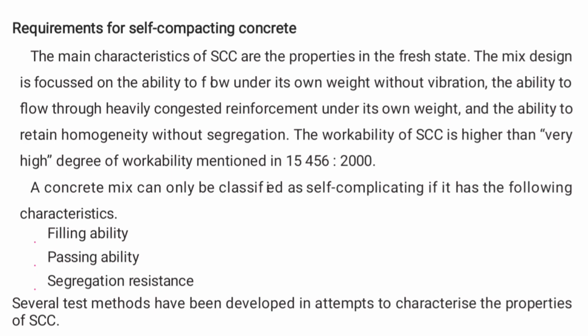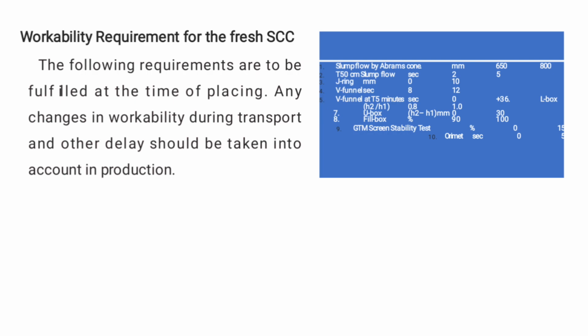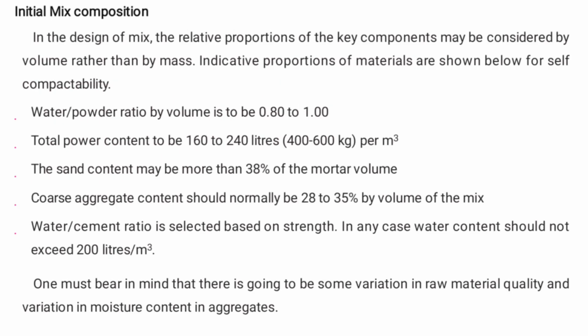A concrete mix can be classified as self-compacting concrete if it has the following characteristics: filling ability, passing ability, and segregation resistance. The workability of the fresh self-compacting concrete is fulfilled at the time of placing. For the initial mix proportion, the water powder ratio by volume is 0.8 to 1. Total powder content is 160 to 240 liters. The sand content may be more than 38% of the mortar volume. Coarse aggregate content should normally be 28 to 35% by volume of the mix.